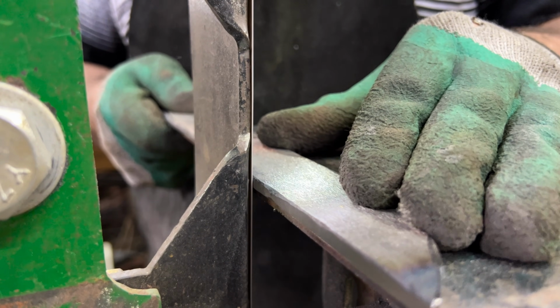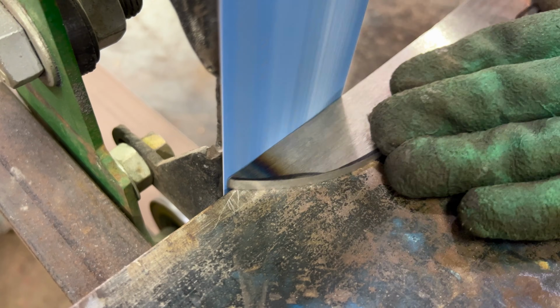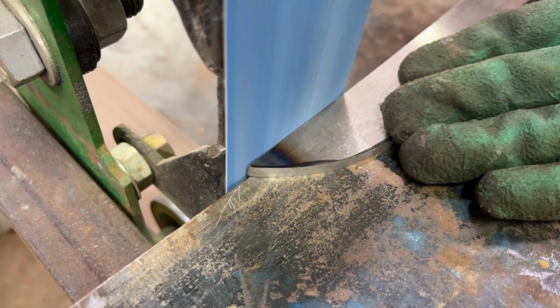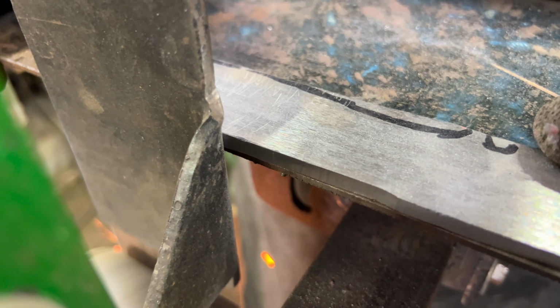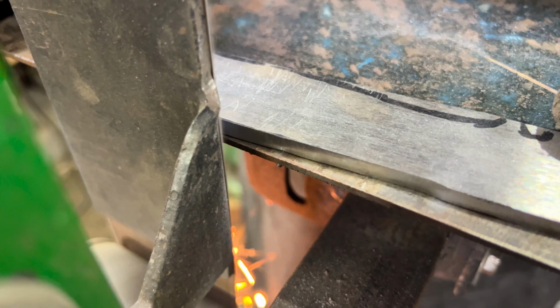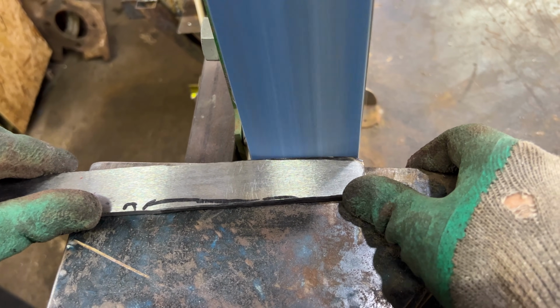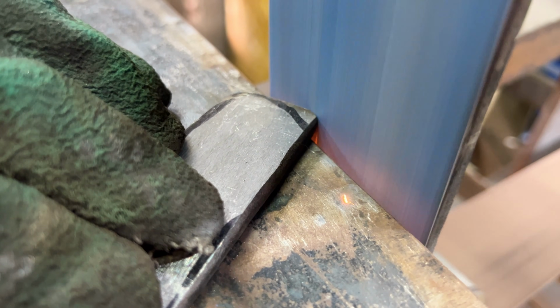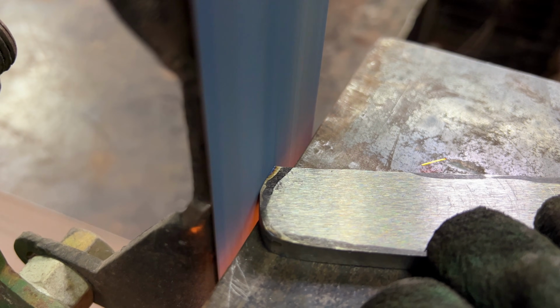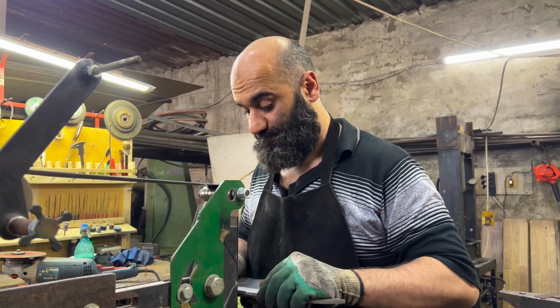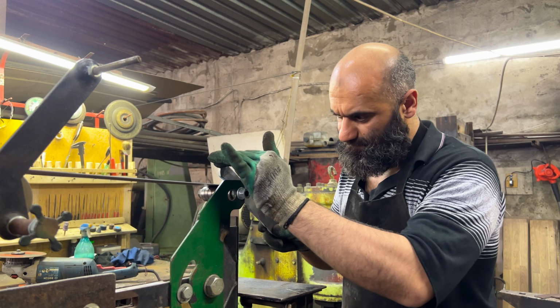Clamp it, weld it shut to keep oxygen out, and back to the forge. This is the most critical weld of the video. We need the jacket to fuse to the core perfectly. I'm hammering it down the spine to set the weld, then flattening it out. Once it's solid, I'm forging the final bevels. Then I hit the surface grinder to get everything perfectly flat and reveal that high carbon center line.